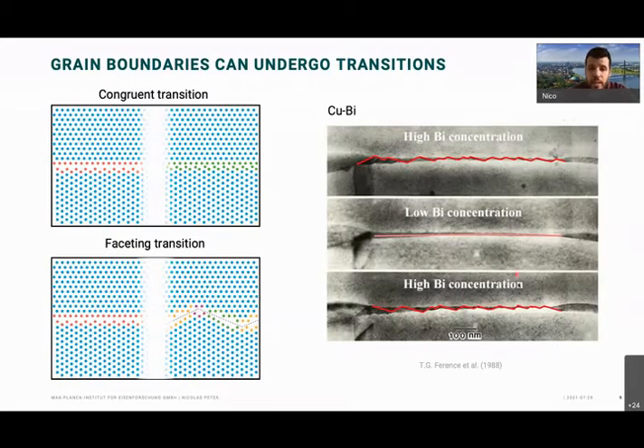So people in the 80s performed a very nice experiment in situ in the TEM, where they had a copper grain boundary and put bismuth inside. And bismuth is known to embrittle the material very much. So if you look here, you can see a nicely faceted grain boundary state for a high bismuth concentration at the grain boundary. And then in situ, they were able to extract bismuth from the grain boundary, switching it back to a flat grain boundary, and then again putting bismuth inside the TEM in the same grain boundary and reproducing the faceted state. So this is a very nice and very unique experiment in literature.